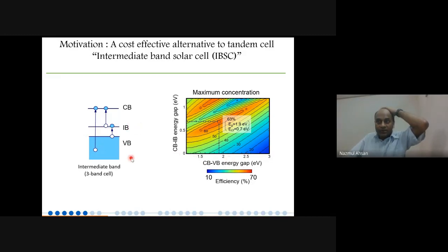in the horizontal axis, the band gap of your original semiconductor, valence band and conduction band. If you see CB for conduction band, VB for valence band, if you, let's say, increase the band gap in the horizontal axis, and if you play with this intermediate band, where you want to position the intermediate band, on top, middle, bottom, how you can design, because this is where you put the IB in contrast to the conduction band. So this is the relative position and this is the relative band gap.